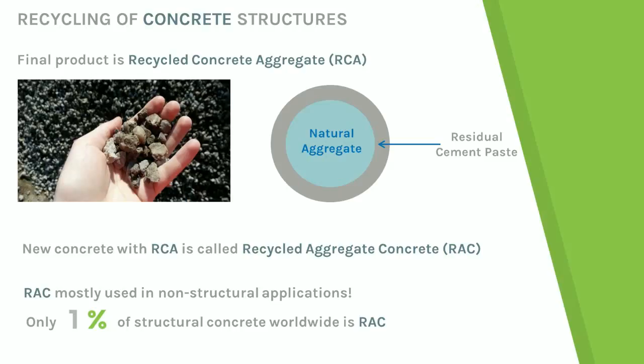Since concrete consists of natural aggregates bound by hardened cement paste, after recycling, a certain amount of this residual cement paste is left bound to the aggregates. This means that the final product of recycling, recycled concrete aggregates, are a two-phase material containing natural aggregates and cement paste. The presence of this residual cement paste causes a certain deterioration of recycled concrete aggregate properties compared with natural aggregates, such as higher porosity, higher water absorption, and potential contamination with chemicals if the old structure was in such an environment.